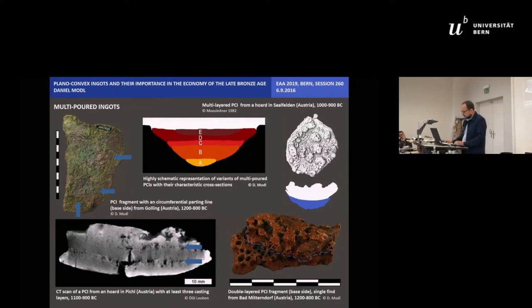Depending on how much time has elapsed between the batches the result is the complete fusion of the metal layers or the formation of internal cooling rims between them. The rims can be described as sharp cracks or blurred gas bubble horizons among the layers.